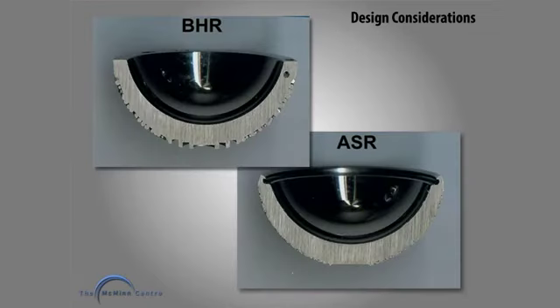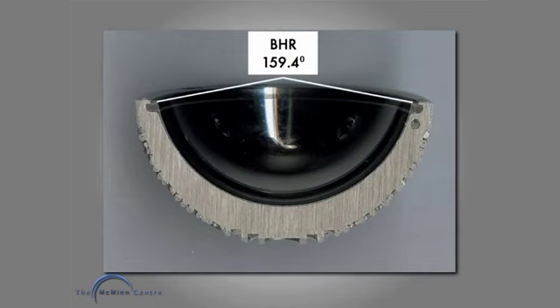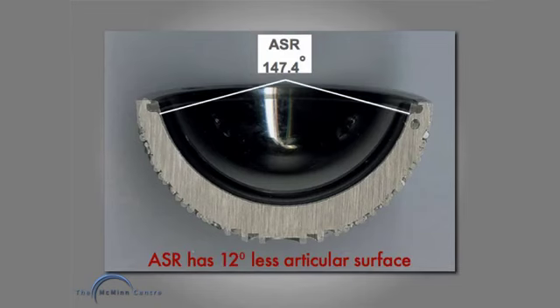So when we look at a slice through a BHR cup and a slice through an ASR cup, the obvious difference is that the ASR has a big groove around the inside edge, and that groove is to attach an introducer. But it has the effect of reducing the articular surface angle, and you can see the BHR 159.4 in this small component, and the ASR of the same size 12 degrees less. 12 degrees less articular sector angle means that you only need a mild bit of acetabular component malposition and you get edge wear. And edge wear was a very potent failure mechanism of the ASR resurfacing device.